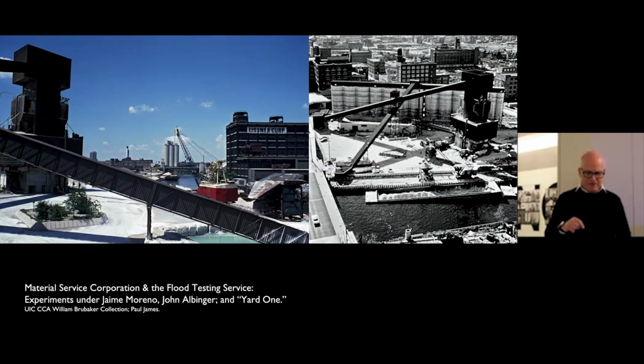Their yard, so-called Yard 1 in Chicago, is located on the Chicago River. So they can bring in aggregate from a wide range of sources, not only from Thornton Quarry, but they can experiment with aggregate from Minnesota, Michigan, other places on the Great Lakes. And it is only 15 minutes from the Loop. So it's a short drive for the trucks to take the material to the job site, to get it placed, but also tested really rapidly. This becomes, I think, the most important concrete laboratory in the country over the next 20 years or so.